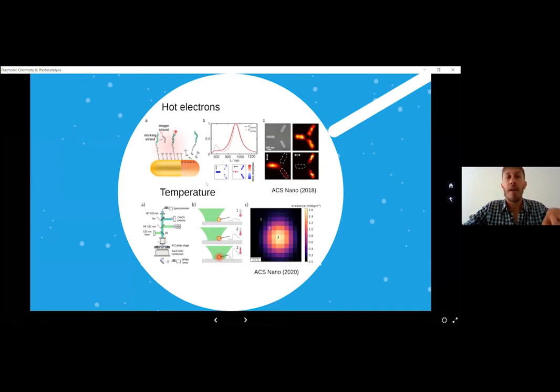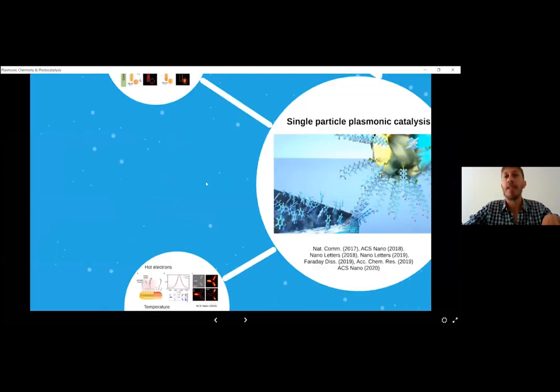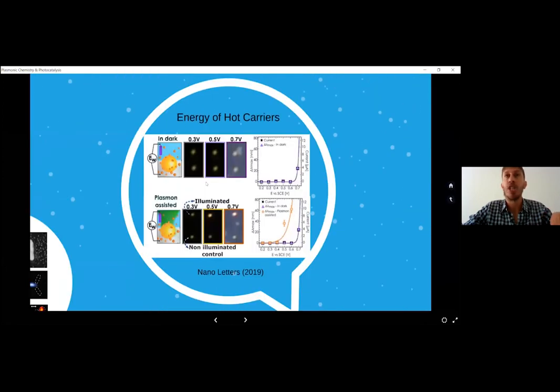Furthermore, besides hot electrons and temperature, we have also developed methods at the single particle level to track the energy of the hot carriers. Here we combined dark field spectroscopy and microscopy with an electrochemical cell, and we were able to track the energy of these hot carriers in a given reaction at the single particle level.